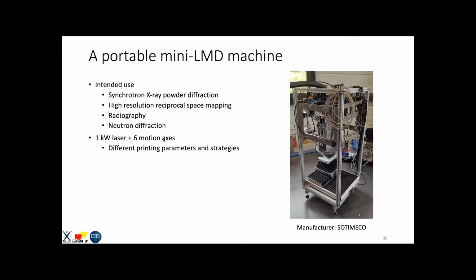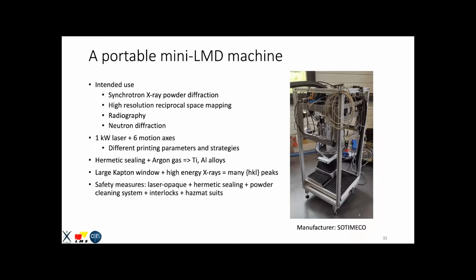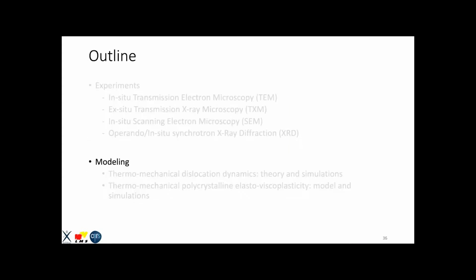So with the 1 kilowatt laser and 6 motion axis, we have different printing parameters and strategies that are possible. The hermetic sealing with argon gas allows us to do titanium and aluminum alloys together with steels and nickel-based alloys, of course. And the large Kapton window with high energy X-rays will allow us to map many different peaks, to measure many different HKL peaks. And we have a bunch of safety measures around it. And we have 2 experiments scheduled in fall 2021. So we are looking forward to this.